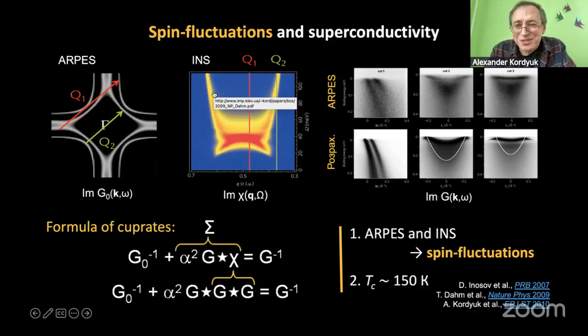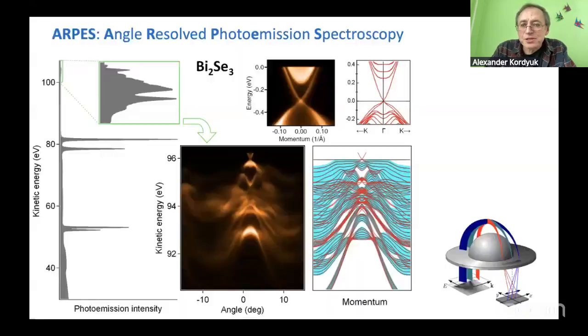I will now explain what this electronic structure is, because I started just to speak about it, but I understand that I need to explain it. So what is electronic structure? Actually, the photoemission experiment, which is now my favorite method, is based on the photoelectric effect. If you have photons with certain energy, you shine them on a sample and you excite electrons, and you apply the energy conservation law. If you know the energy of the photon, it is absorbed, and you have a photoelectron. You can measure its kinetic energy, and the difference between the energy of the photon and the kinetic energy of the electron is the so-called work function, but it is also the binding energy of the electron in the solid.